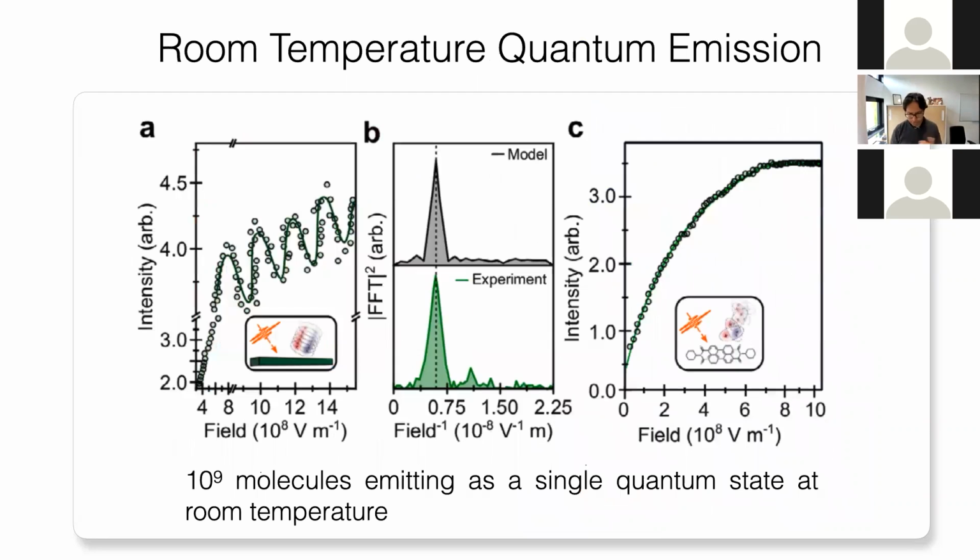And we did further measurements to show this. Essentially, this is a measurement of time-averaged photoluminescence versus intensity of excitation. If you take single molecules or solutions or disordered films and you measure photoluminescence, you classically see a curve like this. I increase my laser power and my photoluminescence increases, and at some point I saturate the material. I have a lot of annihilation in the material now, and my curve saturates. This is what you'd expect from any kind of laser dye, any organic semiconductor.